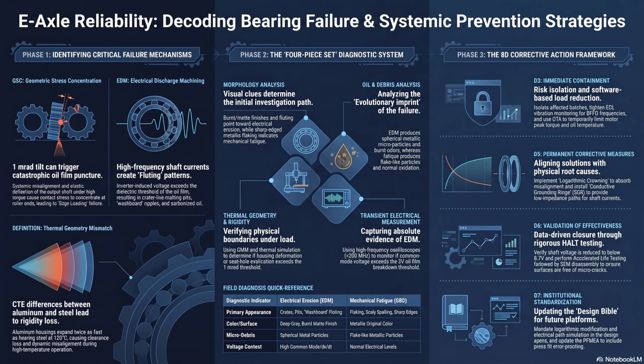Yeah. But there's a hurdle, the microscopic film of oil. Oil is a dielectric, it's an insulator. So it doesn't conduct electricity. Right, so the stray voltage builds up on the shaft, trapped by the oil, until the pressure is so high it just punches through, like a spark plug firing. That is the exact mechanism. When the voltage exceeds the dielectric breakdown threshold of that specific oil film, it arcs across the gap. Microscopic lightning bolts striking the surface of the steel bearing thousands of times a second.